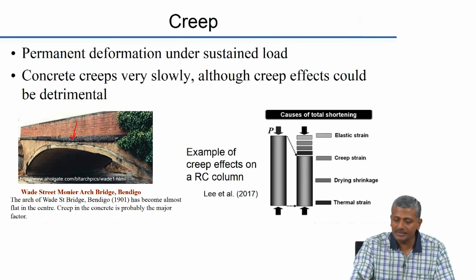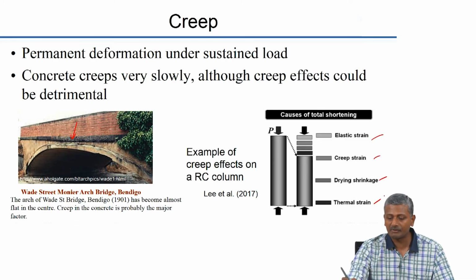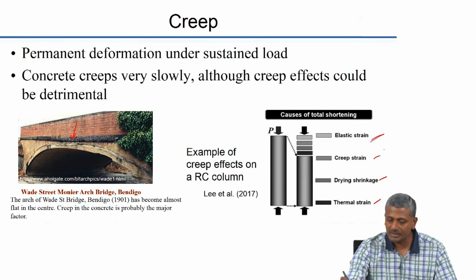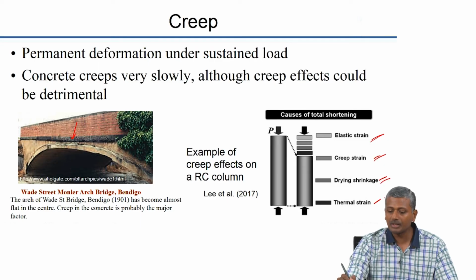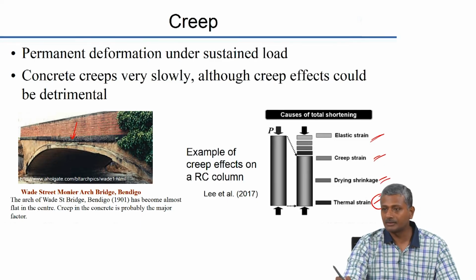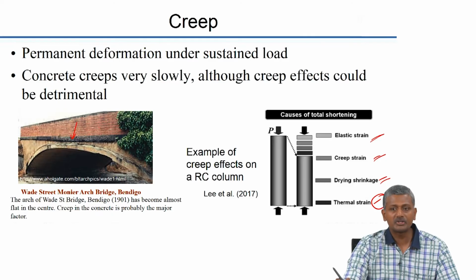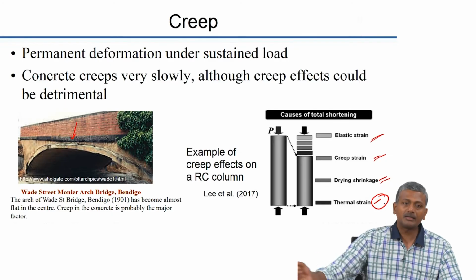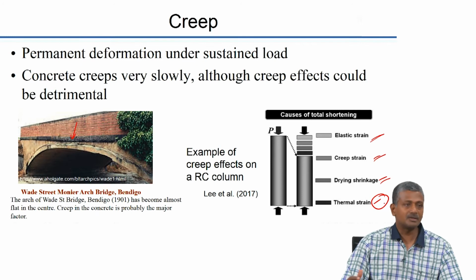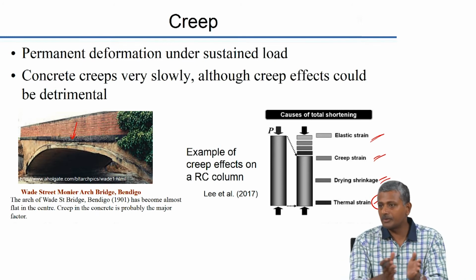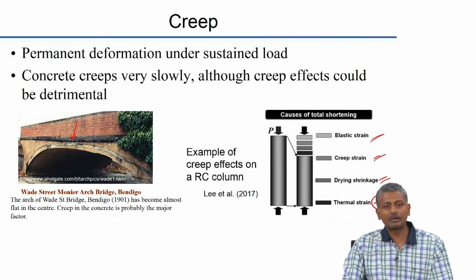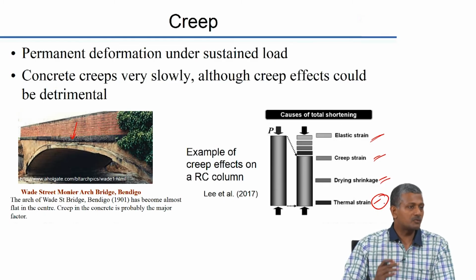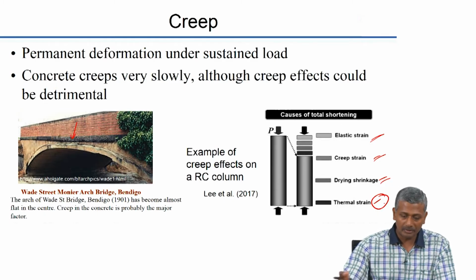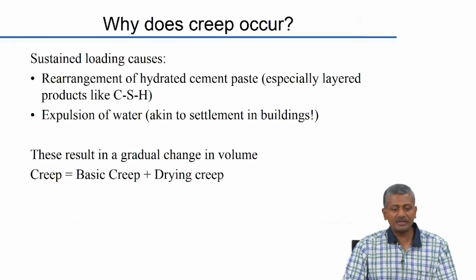Okay. So, here this is an example of what is happening in the case of a column which is loaded in compression. So, you have several different components as we are talking about. You have elastic strain, you have creep strain, drying shrinkage, and you may also get thermal strain depending upon the temperature at the time of concreting and the temperature subjected to in the long term. But the thermal strain, as you can imagine, will happen much earlier in the life cycle of the material as opposed to creep strain, which takes years to accumulate. So, obviously this is a rephrasing of the same thing.